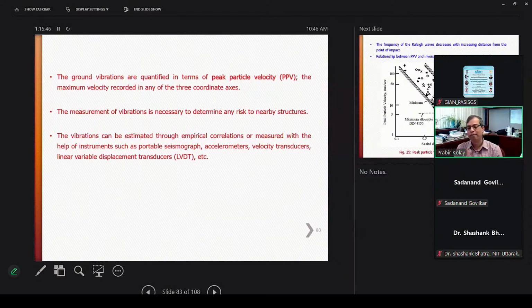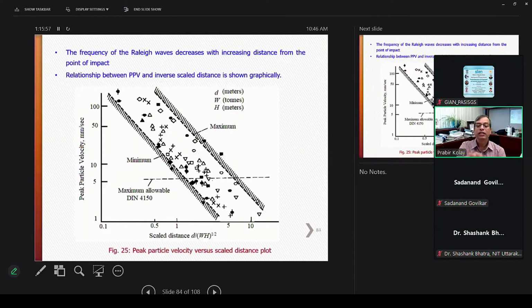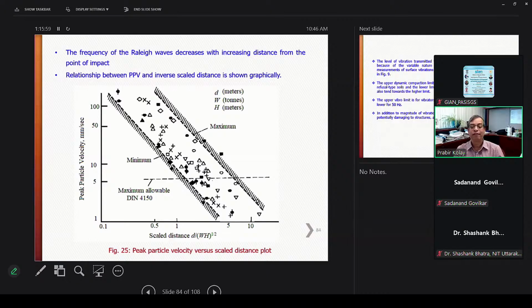Vibration can be estimated through empirical correlations, measured with the help of instruments like a portable seismograph, accelerometer, velocity transducer, or simple LVDT. This will give you a guideline, like peak particle velocity and the scaled distance. The frequency of the Rayleigh waves decreases with increasing distance from the point of impact. As you go farther, the impact is less. The relationship between peak particle velocity and inverse scaled distance is shown graphically here. You can adjust everything depending on the instrument.